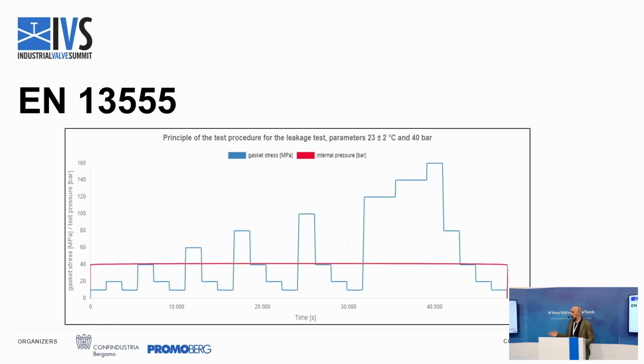And speaking of graphite and graphite seals, EN 13555 is one of the most important certification for the gaskets, for the flat gaskets and the graphite gaskets in the pipelines or in a flange connection. Usually this test is run with helium. It can be done also with methane, but helium is of course more challenging. It is run at ambient temperature, 23 degrees, with 40 bars.